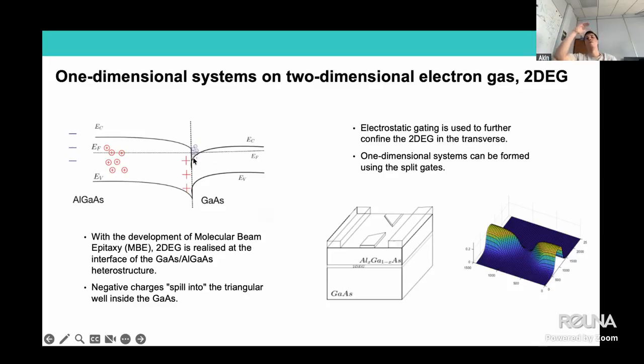So those electrons are now confined in the z direction, and then at low temperatures we can reach the two-dimensional ground state. So they're fully confined in the z direction. They can move in the plane, so they can be explained two-dimensionally. Through electron beam lithography and surface gates, we can apply negative potential and confine this channel. So here there is a basic electrostatic solution where top gates would have a negative gate voltage, so that the electrons would see that as a barrier and then confine into that saddle point in the middle. And therefore we get a one-dimensional system, or quasi one-dimensional system.